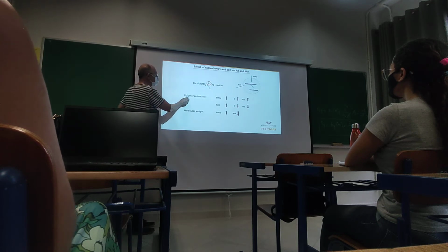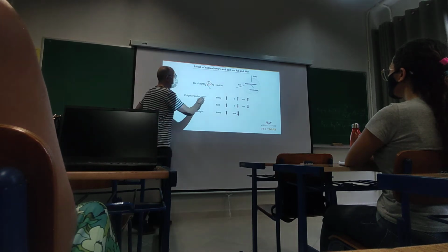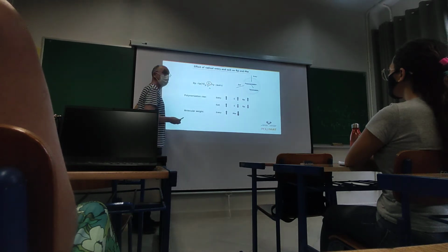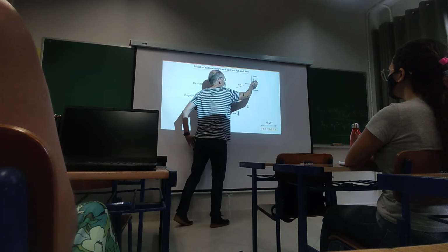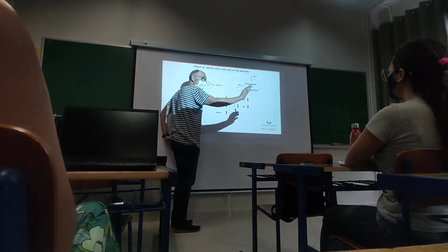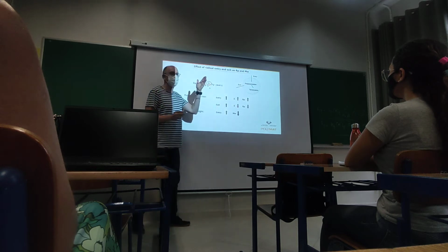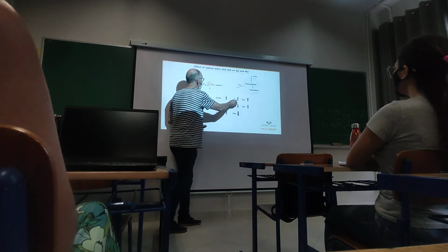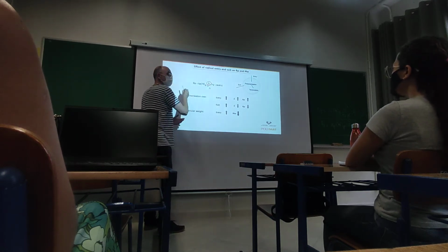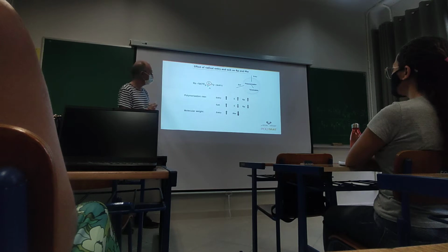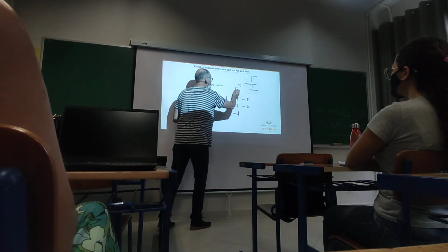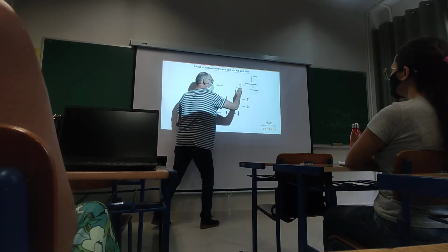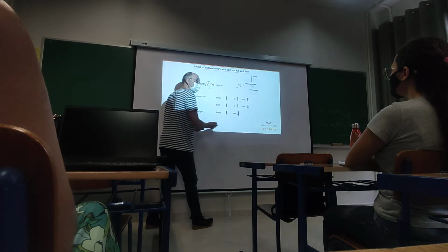For instance, if we analyze the polymerization rate, and the radical entry increases while exit and termination remain the same, the average number of radicals per particle will increase. We will have more radicals on average. And therefore, according to this equation, if this increases, the polymerization rate will increase. Now, if the exit increases and the rest stays the same, the average number of radicals will decrease because we will have more exit, there will be fewer radicals inside, and the polymerization rate will decrease.